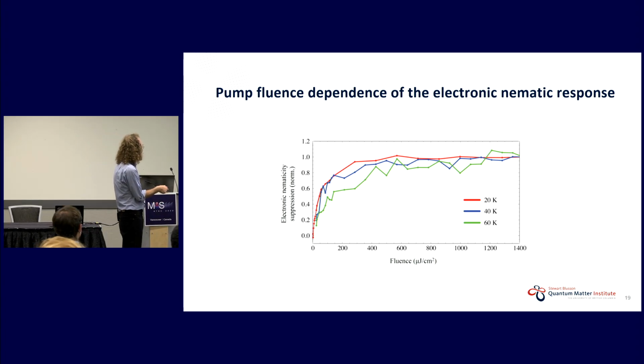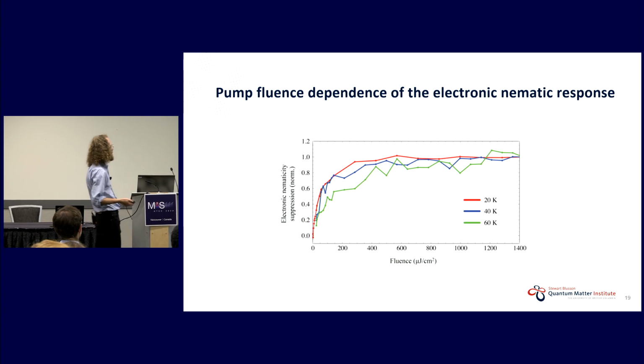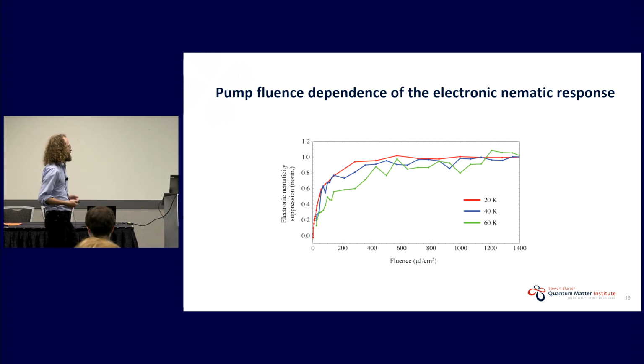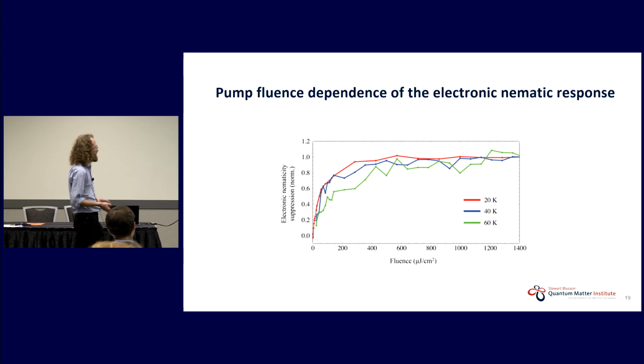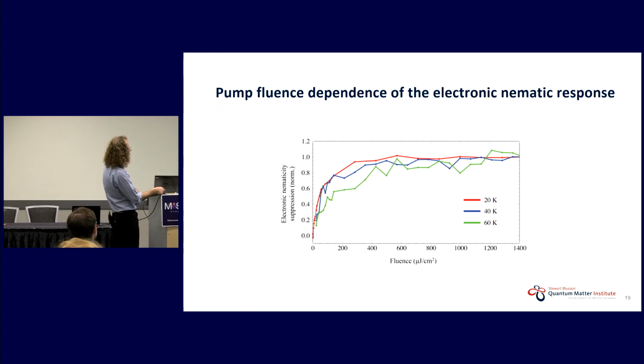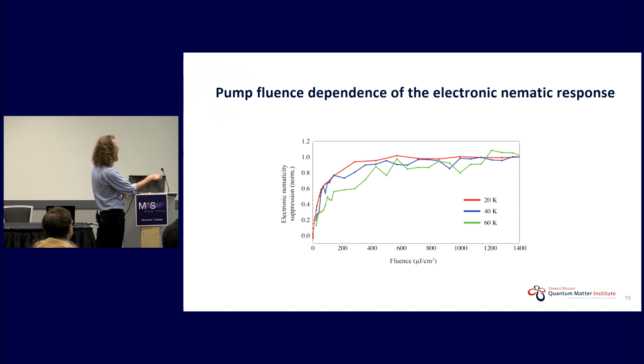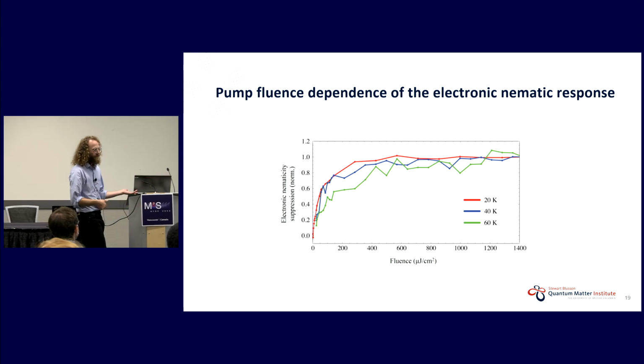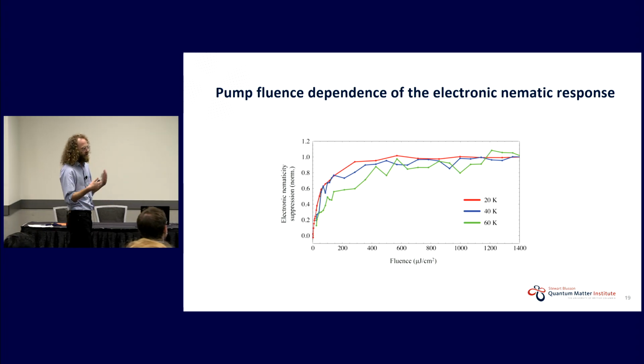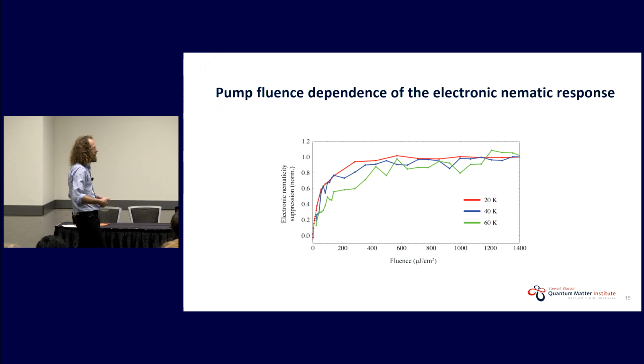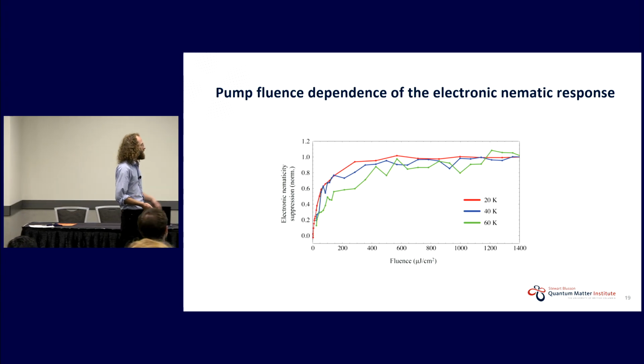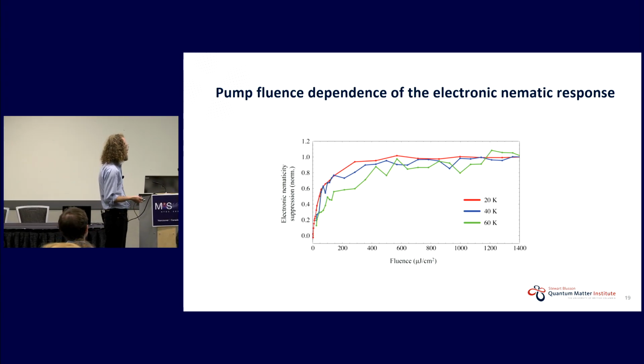And the only thing that I want to point out here is, if this effect were maybe a pure thermal effect associated with transient electronic temperatures, you might expect that actually the saturation fluence would shift to lower fluences for higher temperatures. So maybe this is evidence that this is not purely thermal, that we're somehow in a non-thermal regime when we're doing this experiment. But maybe there's something more behind that.